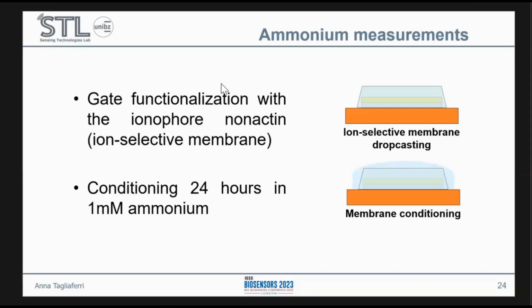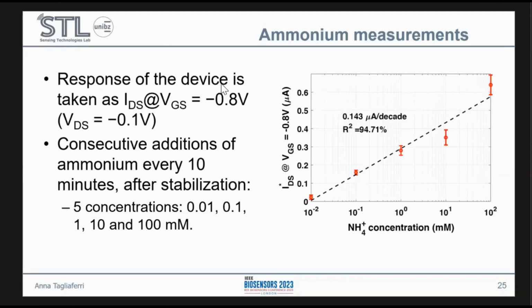We then measured 5 different concentrations of ammonium, and the response of the device was taken at a fixed gate voltage of -0.8 volts and a fixed drain voltage of -0.1 volts. We did 5 consecutive additions of ammonium every 10 minutes after the stabilization time, and we see that we get a linear response over the whole range of concentrations that we have tested, with a coefficient of determination close to 95%.